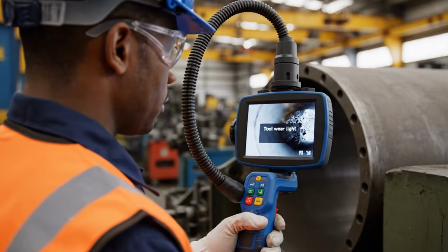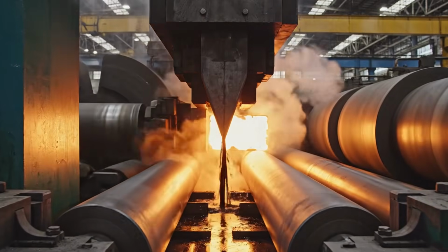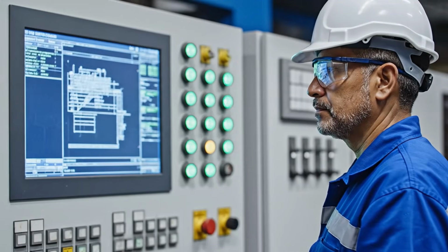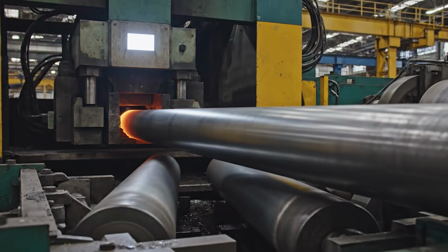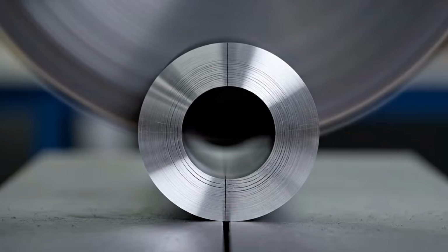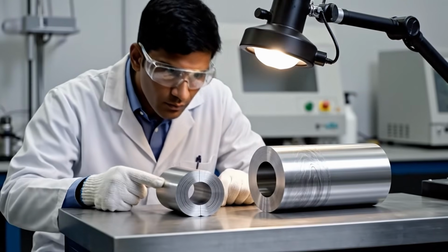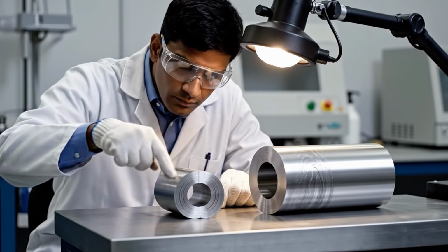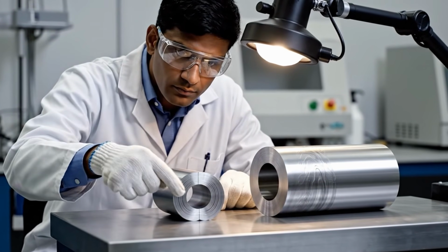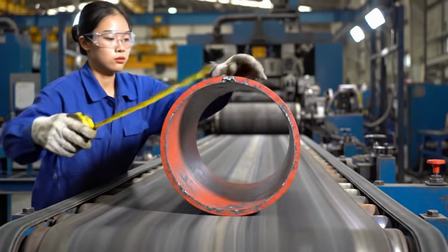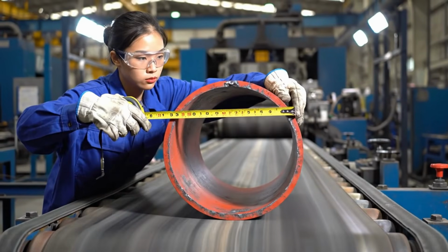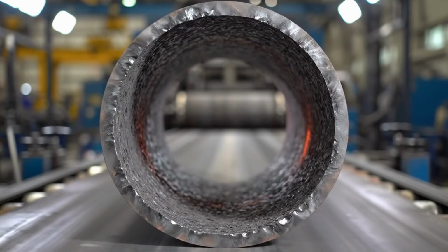If the temperature drops too much, the steel offers more resistance and defects appear. If the plug is not in optimal condition, the interior of the hollow acquires marks, drags, or undue roughness. Everything must be aligned. Roller speed, feed angle, lubrication, temperature, tool condition, and billet geometry. The exit of the piercer already shows something essential.